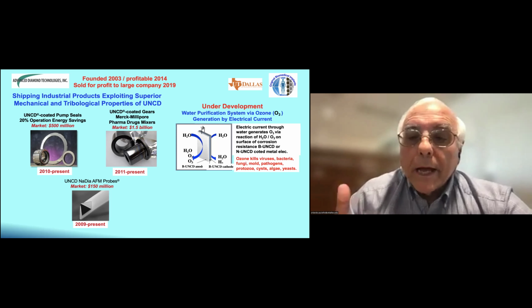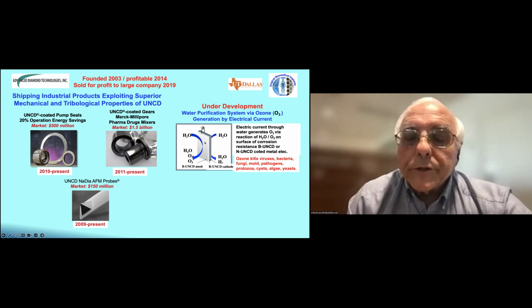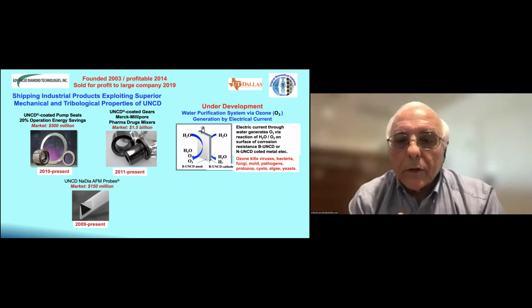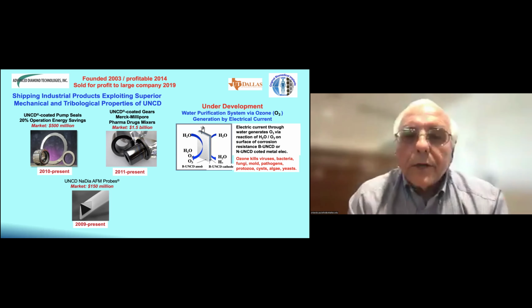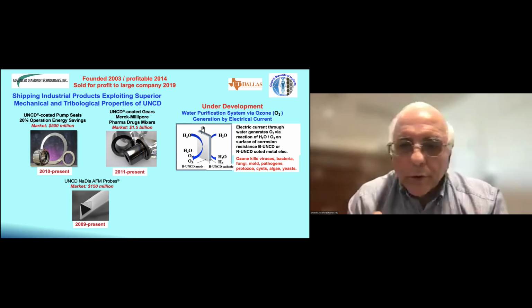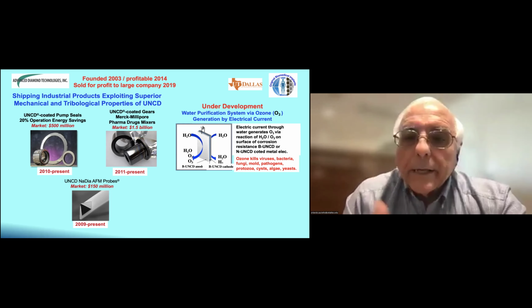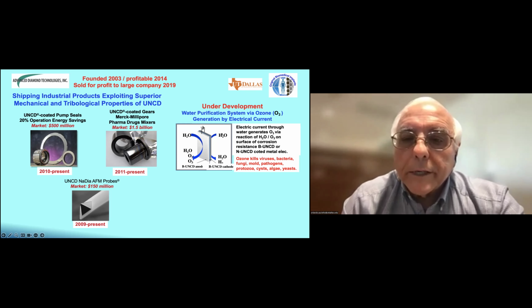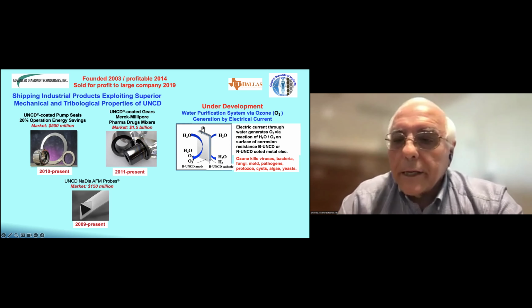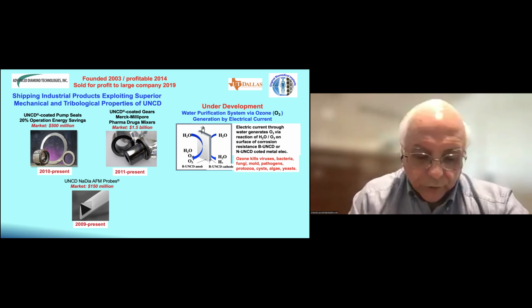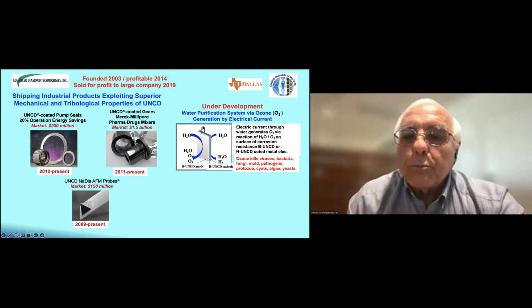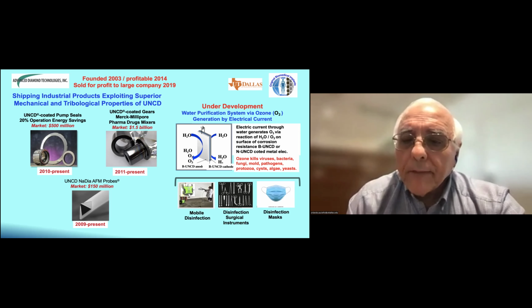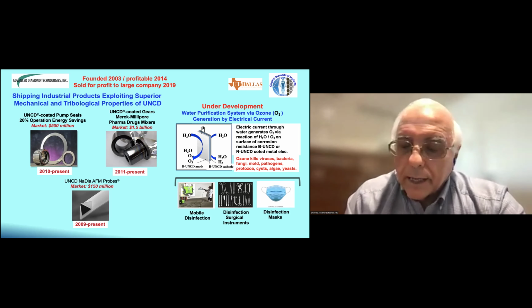And now what we are working on extensively is developing this water purification system that involves boron doped UNCD coating on metals. Our UNCD coating cannot be corroded by any fluid, water, anything, including hydrofluoric acid. So what we demonstrated here is that by passing a current through boron doped UNCD metal electrodes, we can create ozone, and ozone kills all bacteria, fungi, and everything in water. So this is a process that may allow water purification in 5 to 10 minutes, and also cleaning of surgical instruments, mobile disinfection, and other things.